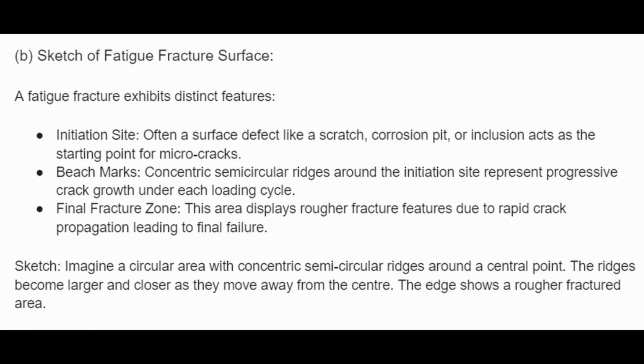A fatigue fracture exhibits distinct features. 1. Initiation site. Often a surface defect like a scratch, corrosion pit, or inclusion acts as the starting point for micro cracks. 2. Beach marks. Concentric semicircular ridges around the initiation site represent progressive crack growth under each loading cycle. 3. Final fracture zone. This area displays rougher fracture features due to rapid crack propagation leading to final failure.